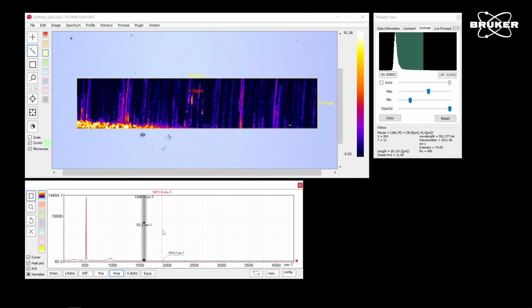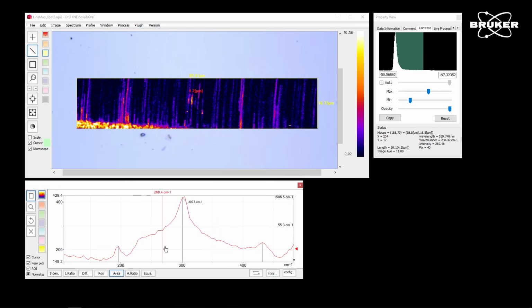We've already talked about the G to D ratios and their meanings. Here, something new appears in these nanotubes, since it's not planar, but more or less cylindrical. We have radial breathing modes. These radial breathing modes appear at the lower wave number range below 300 wave numbers.